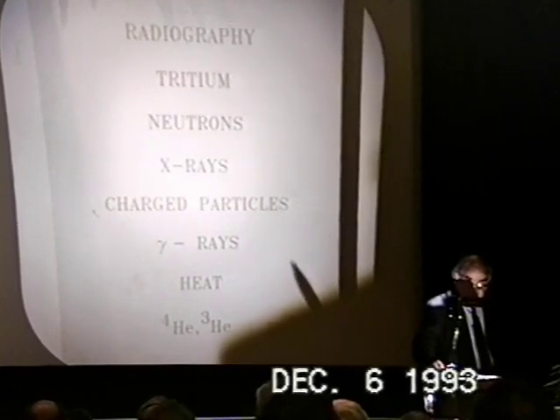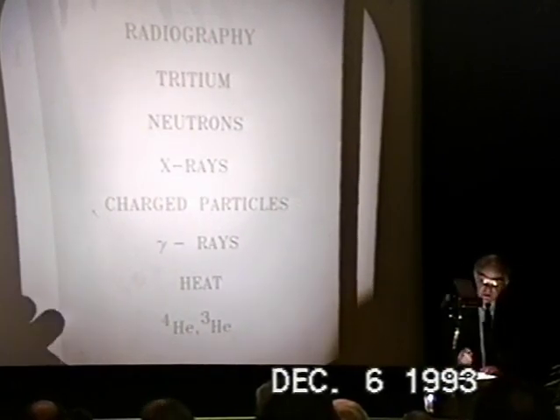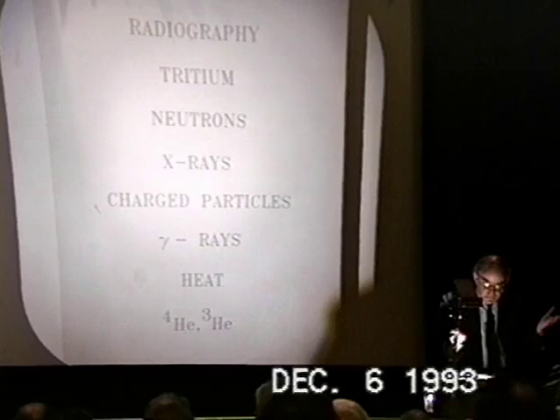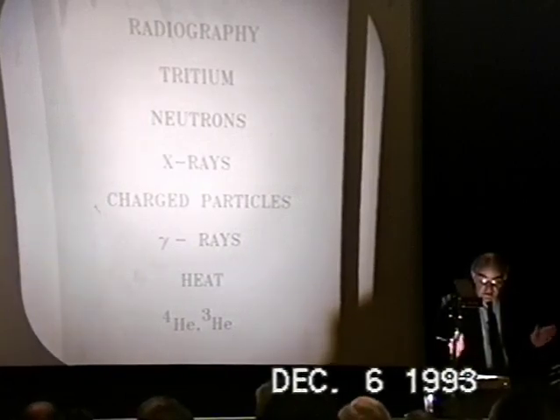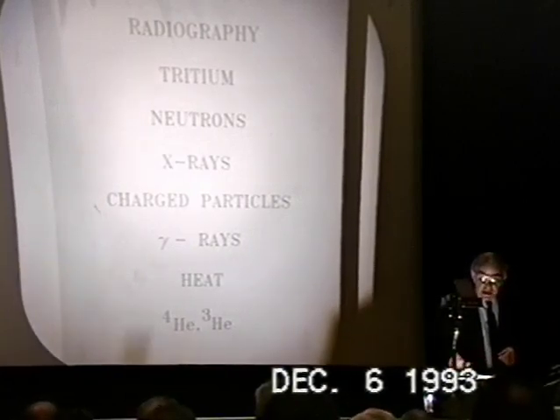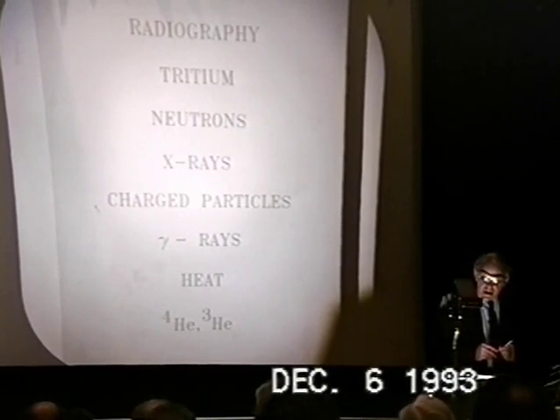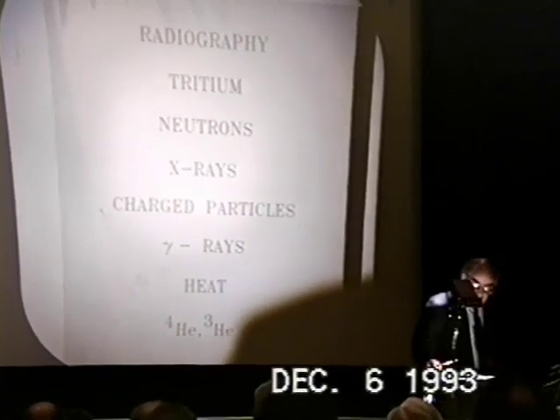Well, of course, what we were looking for originally were some signatures of the process. If we look at this in hindsight, we were looking for tritium, neutrons, radiography, charged particles. We did actually look for some of these. But what we found, to our surprise, was an enormously high level of excess heat, over and above that which you can explain by the electrical process.